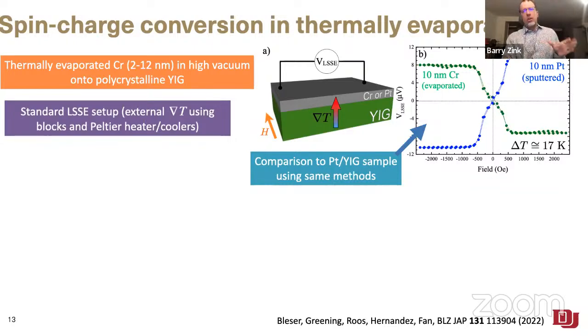So we did a very, very standard manifestation of the longitudinal spin Seebeck effect. So we thermally evaporated chromium in a bunch of different thicknesses onto polycrystalline YIG slabs. We smashed them between copper blocks with Peltier elements, applied a thermal gradient and measured the voltages. This was all done in my colleague Shin-Fan's lab. He does these sort of standard spin Seebeck experiments for various things much more frequently than I; we hadn't really done them. And so we were working with him. It was great.